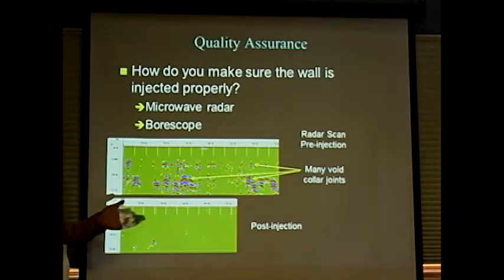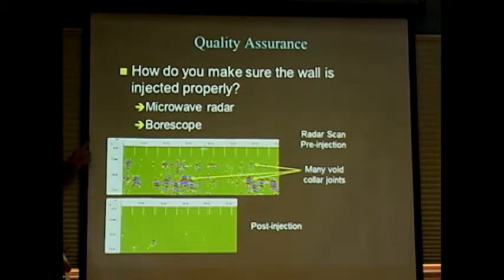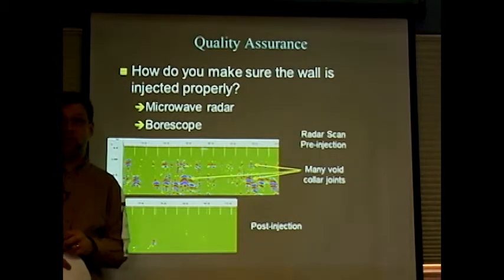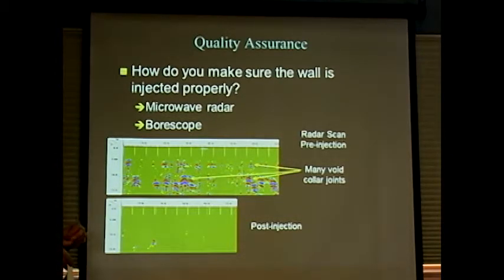And we saw the results of some condition survey radar. Here are some other radar traces with a different color scheme. I like this one because it's really easy to see, I think. Before injection, scanning down the wall, 15-inch depth here. All of these little reflections mean voids. Lots of voids in the collar joints. And same spot after injection, nearly completely solid. And that's our goal. I don't think the original designer intended there to be voids inside the wall and intended the collar joints to be empty. And our goal then was accomplished in providing a solid wall and the voids inside that wall being filled with a nice compatible material that we'll see in a moment.